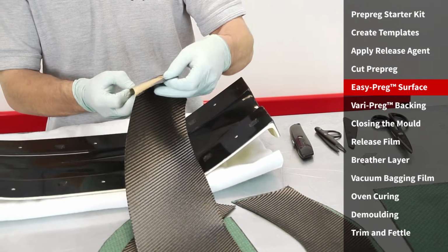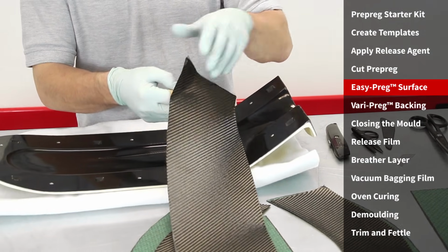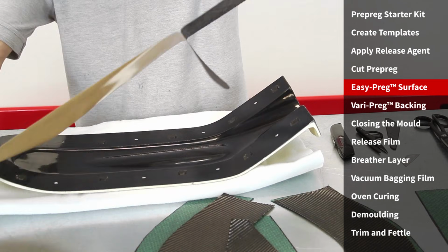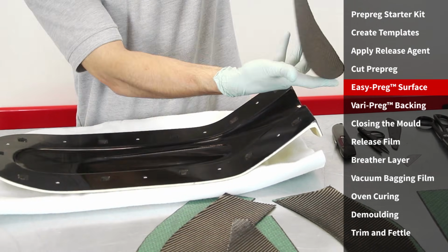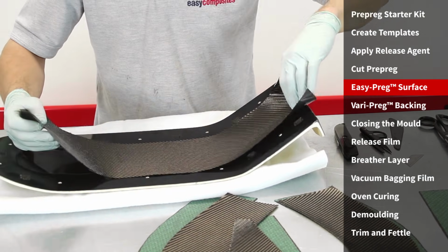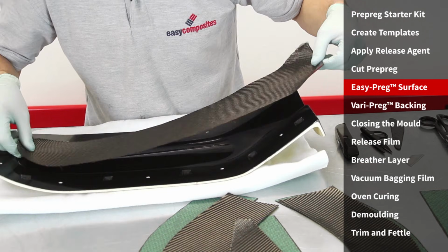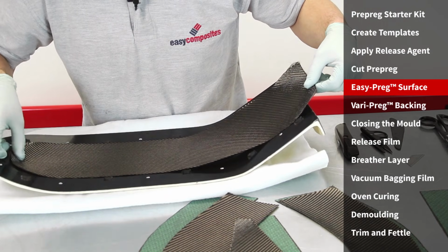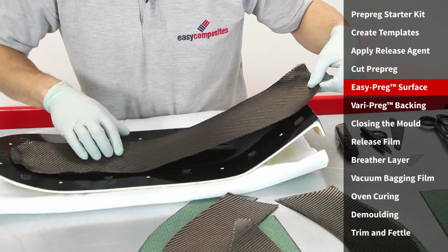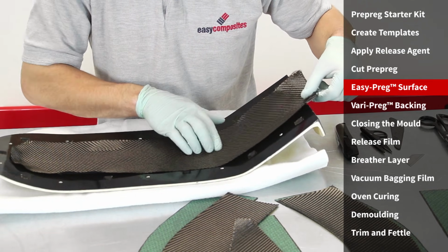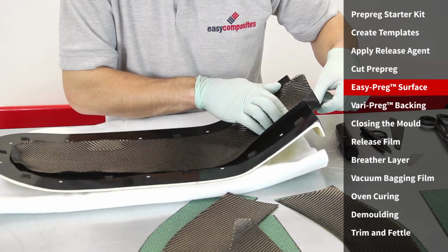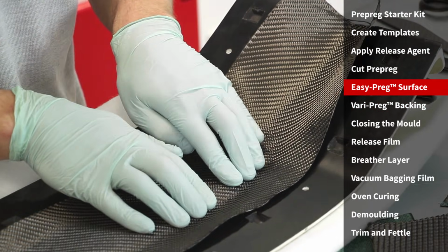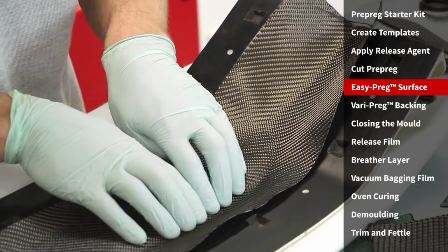With our kit of prepreg ready and our moulds prepared, we're now ready to start the layup. First, loosely place the material into the mould, ensuring that it is accurately in position before firmly pressing against the surface. It is good practice to work the material from the centre outwards. This ensures that the material is in intimate contact with the entire mould surface. Any air pockets or bridging of the fabric in corners must be driven out.